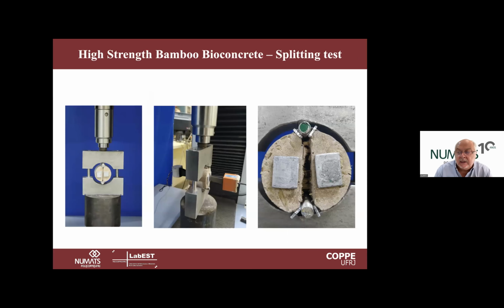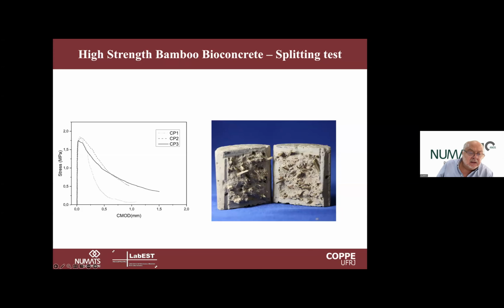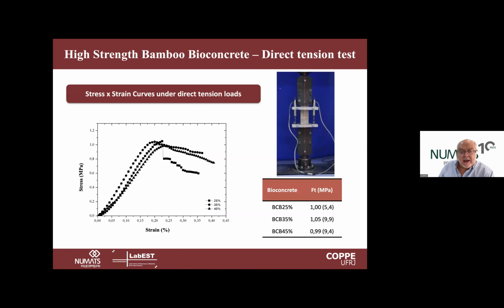We also did the test under indirect tension to see the fracture energy of this material, and also to determine the bridge effect that these filaments can promote here. We see the post-cracking zone, the effect of the bamboo filaments working to control the crack opening under indirect tension and also under direct tension.